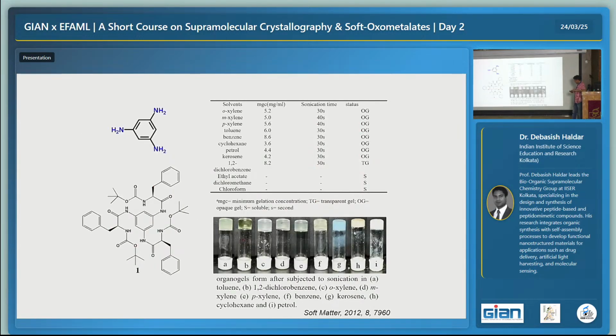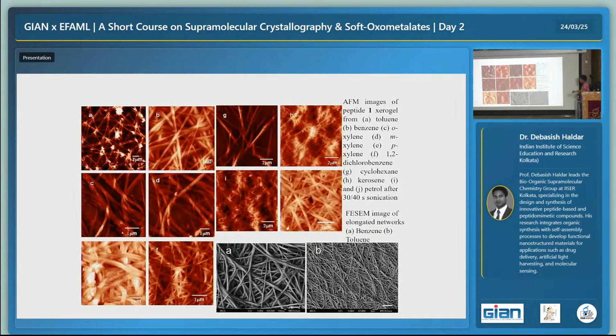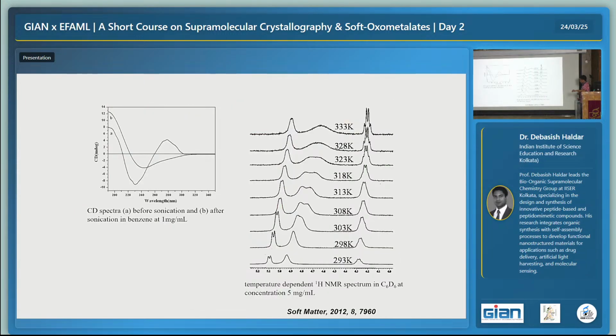And then again, this is another example where we have changed the core with triamine, but this core again helps to form the gel in different organic solvents, and we have utilized that gel. From different organic solvents we get different thickness and morphology of the fiber, differing from one solvent to another. So it is not only the property of the material, but also the property of the environment, how you are changing your solvent, how the solvent is interacting with your molecules, and in that way the gel forms. And here from the AFM again we see the very dense gel fiber.